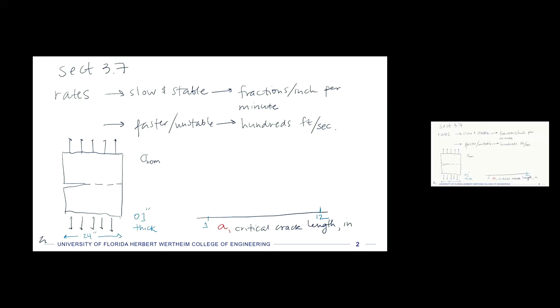It's being pulled. And then we can plot on the y-axis here the gross failure stress. So what was the stress at which that crack just propagated all the way across quickly and the part failed? This is going to be in kpsi, and it's going to go up to about 60 here, and then down to 0, so I have 20, 40, 60. When I plot this, it's going to look a little bit like those SN curves, but put that out of your mind because we're talking about something different now.